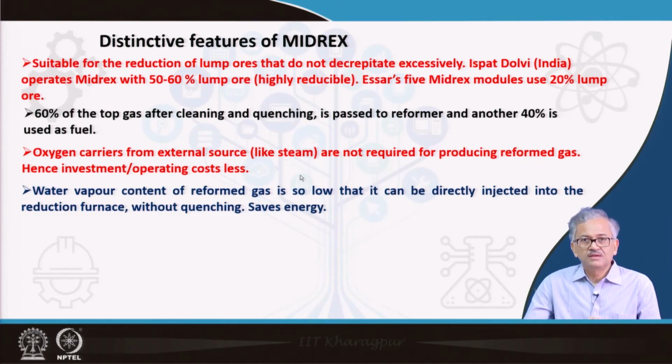And another important thing is that the reform gas that you produce does not contain any moisture, because you are doing CO2 reforming. Natural gas is reformed by the CO2. So the reform gas does not contain moisture, so you don't require any dehumidifier. So that is the thing.